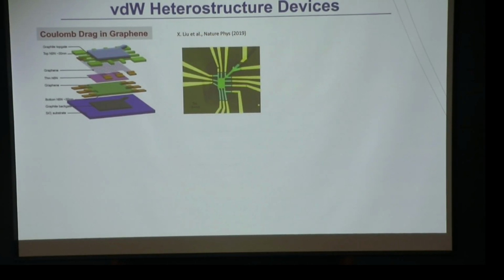For example, you can stack them together into multiple layers, right? Here comes graphene, another graphene, and you can put them together with some separation layer. You can see there's a thin layer of boron nitride separating them. If you use reasonable thicknesses, the two layers are well separated and there is not much tunneling.